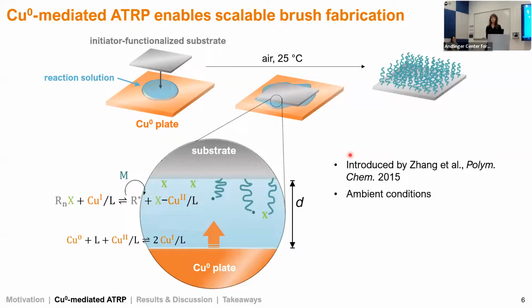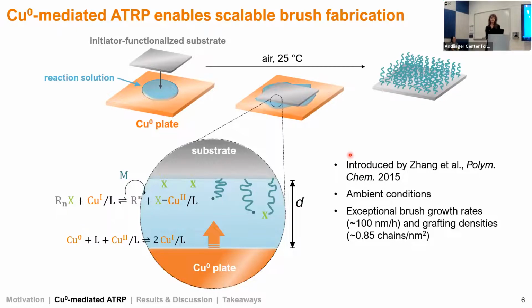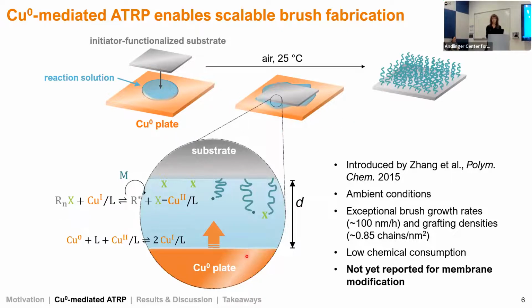And importantly, we can achieve polymer brush grafting under ambient conditions, so no deoxygenation required. Exceptional brush growth rates and grafting densities have been reported in the literature. And chemical consumption is very low because only a very small volume of reaction solution is required just to fill this thin gap between the substrate and plate. So it has yet to be reported, to our knowledge, for membrane modification. So I'm going to show you that today.